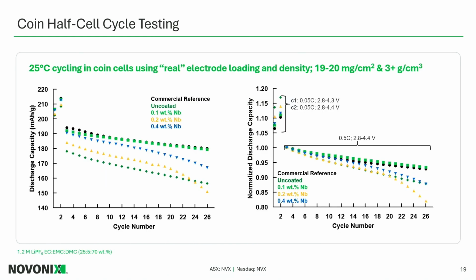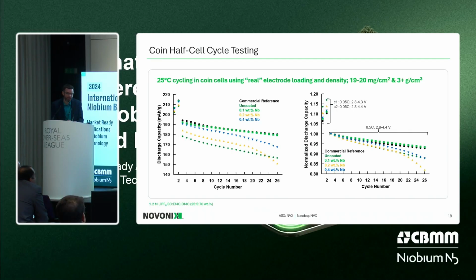So these data are raw coin half-cell measurements done on those materials from the previous slide. The left-hand part of the slide is the absolute value of discharge capacity. The right-hand side is the normalized version. And what you can see right away is the 0.1 weight percent niobium oxide surface coating is quite competitive and comparable to the commercial reference NMC811 powder.